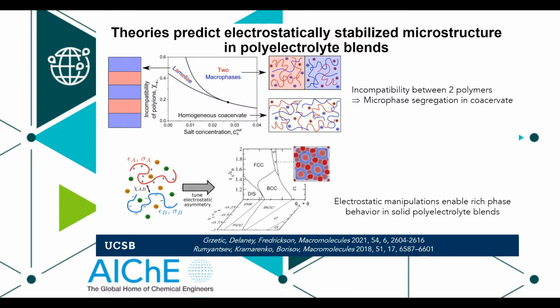Many of our theory colleagues had predicted that when you make a coacervate, it's not just going to be a homogeneous mixture of your two polymers. There will be some structuring driven by the electrostatic interaction and the desire of the backbones to separate a little bit. That might make nanometer scale lamellae. It might make some kind of sphere structure, okay?